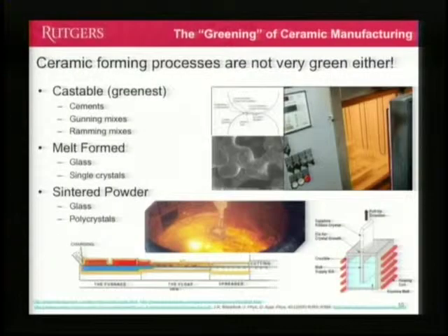Here's a gunning mix that's actually sprayed at a very high temperature, around the temperature that steel is made. These ramming mixes are ones that don't require high temperatures, but they're usually used for high temperature furnaces to fire other things, and they rely on the hardening at that high temperature to give it its high strength. Glasses and single crystals are made by melt-based processes, quite elaborate, quite energy consuming.